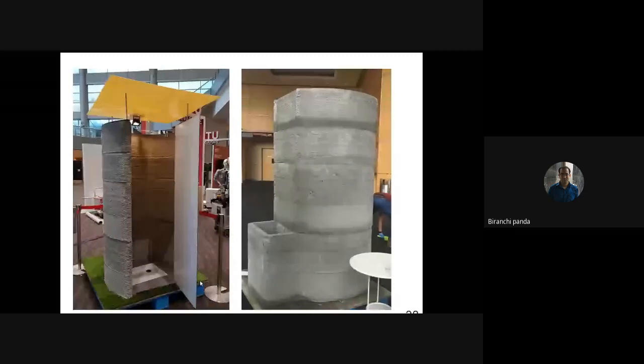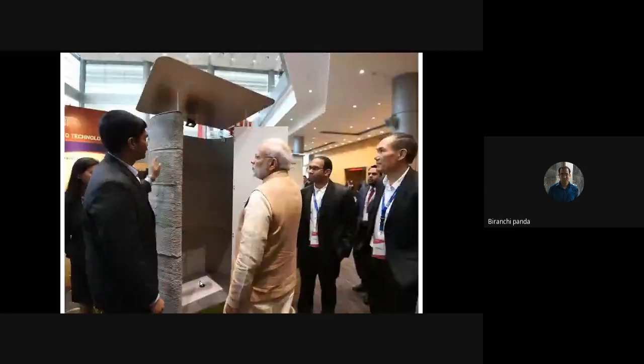This is a 3D printed toilet. That has been printed in just maybe 60 minutes to 1 hour. Normally, if you do casting, it takes 3 to 4 days to have this kind of structure. And we invited our Prime Minister, and he gave very good comments and appreciated our work, that this kind of digital construction technology can really provide affordable or timely structures for many reasons.